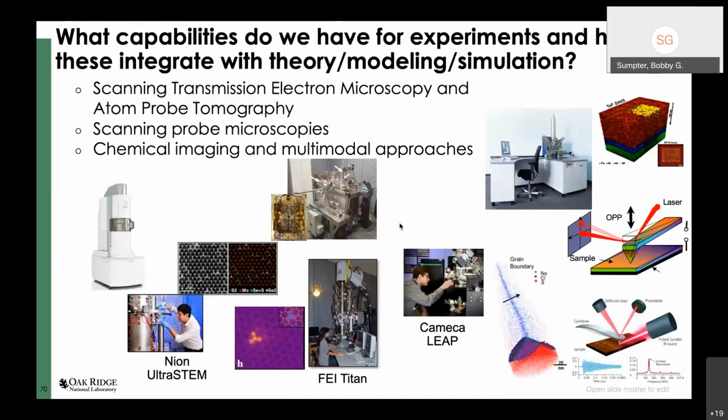Tools that we have currently that allow us to see atoms. There's a whole suite of them: electron microscopies, transmission electron microscopy, scanning transmission electron microscopy. These are getting better and better, with sub-angstrom resolution already, so we can actually see atoms and below atoms. There are new tools, like ultra-low temperature scanning tunneling microscopies, that allow us to probe quantum phenomena directly. And chemical spectroscopies based upon helium ion microscopes or time-of-flight systems allow us not only to see and image things, but to get the actual composition directly.